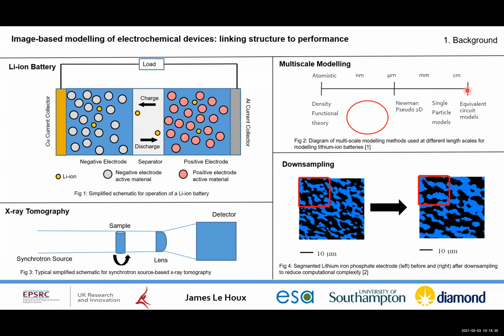And so to do that, we can manufacture real electrodes and then use imaging techniques to obtain these 3D data sets. When we take this to the synchrotron or to the lab-based X-ray tomography, we take our electrode sample, place it in a radiation source, and then fire radiation at it, obtain 2D projections on this detector, rotate the sample, and then we can reconstruct that into a 3D volume to obtain a representation of the microstructure of that material.